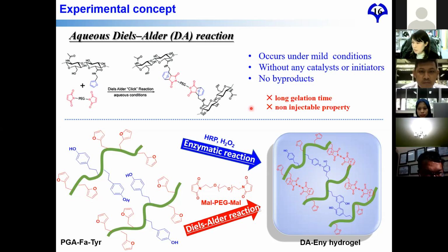Because in the previous work we just increased the gel strength using the DA reaction, but the gel temperature and gelation time is controlled by the diblock and triblock copolymers. So to fix this kind of problem, in this work we use these two kinds of cross-linker to make the PGA network. It's the enzymatic reaction and the Diels-Alder reaction.